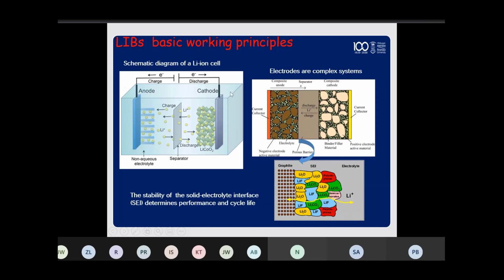What I would like to stress here is that while the whole cell is, of course, a complex system, the electrodes themselves are also complex systems. They are generally composite, so we have a mixture of three main components. There is the active material, the one that intercalates and deintercalates the lithium ions, such as, in this case, graphite. This is mixed with a plasticizer, generally a binder. Most used is PVDF, which is fluorine-based.